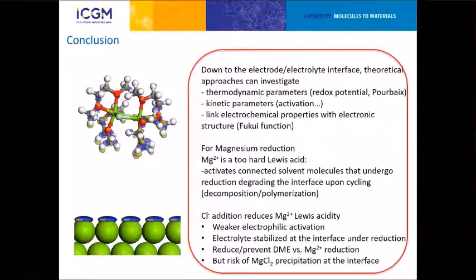Like, did somebody observe the ethylene carbonate polymer that you propose? For ethylene carbonates, there are some experimental observations of really thick layers that were analyzed to be mostly organic. So some kind of ethylene carbonate polymer is coherent with what was observed. And the polymerization of ethylene carbonate with magnesium, which doesn't occur with lithium, is certainly one of the problems of all the solvents that have ring carbonates. And for the DME, there are some observations of ethylene production upon cycling. Of course, the problem with the interface is that it's very difficult to really observe things that are happening mostly 1 nanometer away from your electrodes.